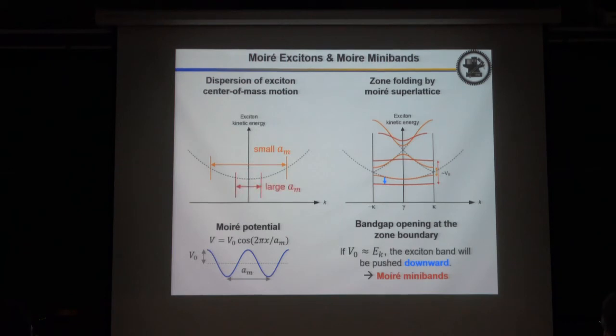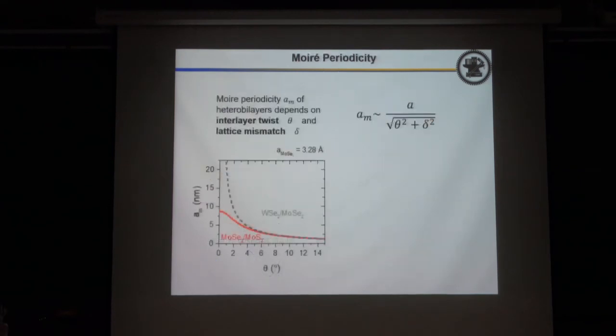On the other hand, if you use a large superlattice, then the zone becomes very small, and then the kinetic energy is also small. So that's why we can use twist angle to change the periodicity, and then it changes the relative amplitude of the Moiré potential to the kinetic energy. So you will see different kinds of energy modulation of the exciton.